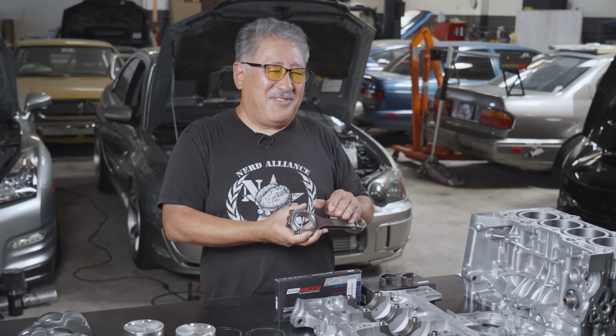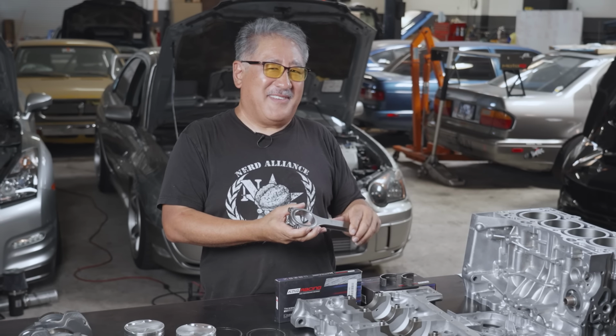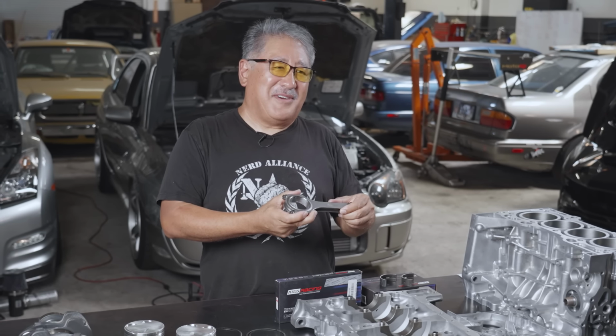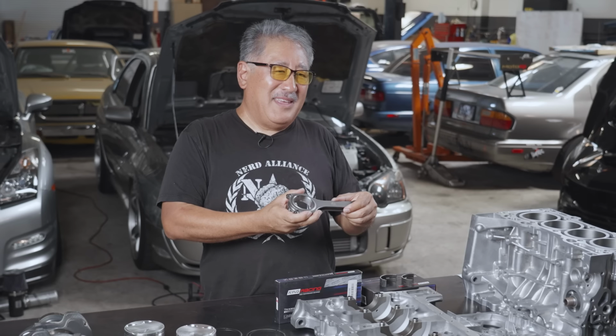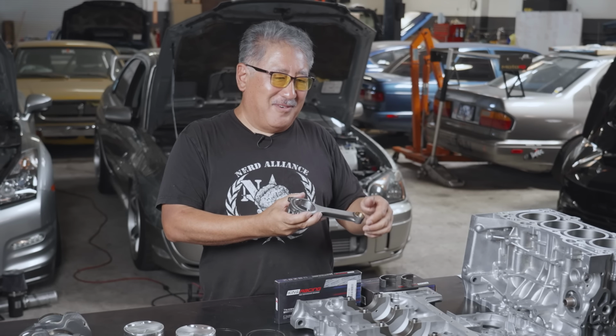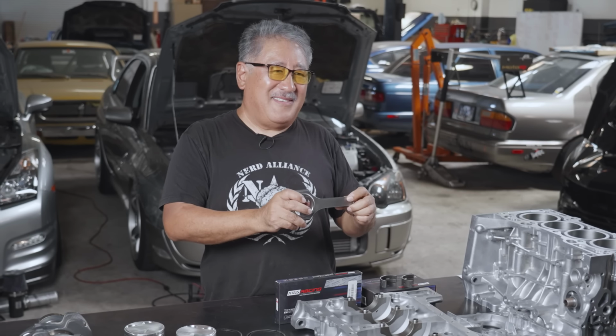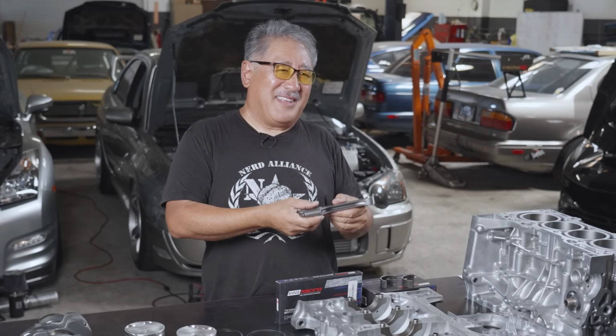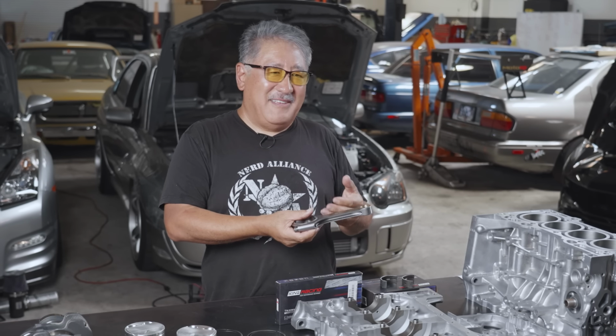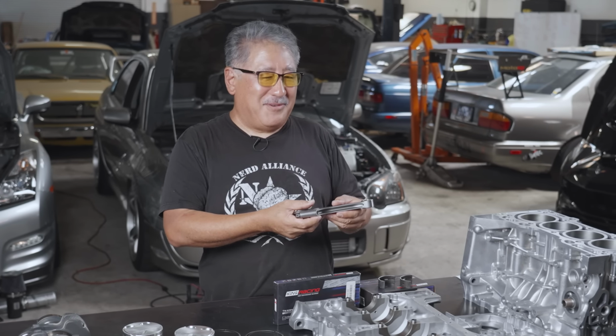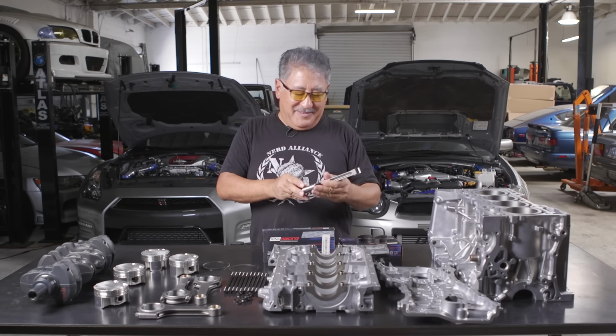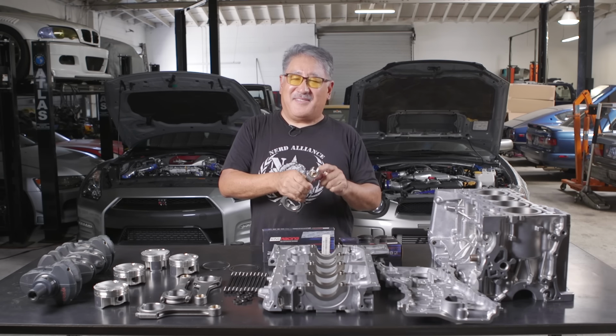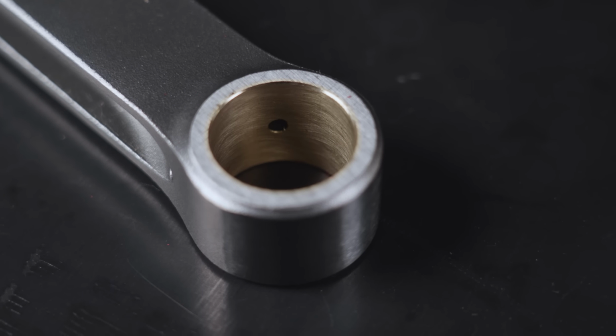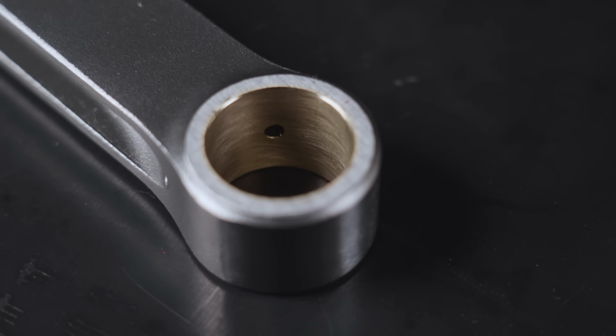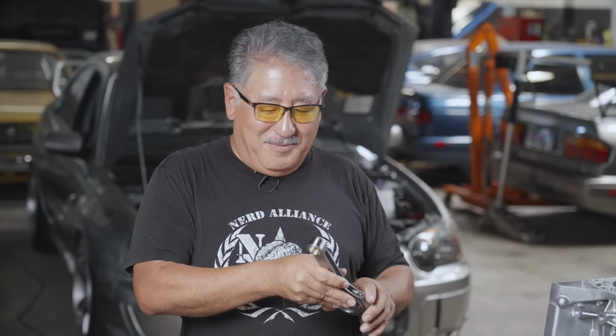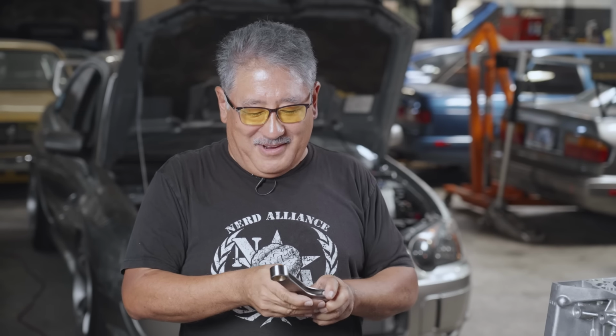Now, when you have compressive stress and a finely grained skin, it's really hard for a crack to get started and propagate throughout the rod. So what that means is the amount of cycles that the rod could take before it breaks is basically doubled with the proper shot peening. Some of the normal things: it has a silicon bronze small end bushing, which is kind of typical for a high quality rod. But most of all, you get all this at a great price.